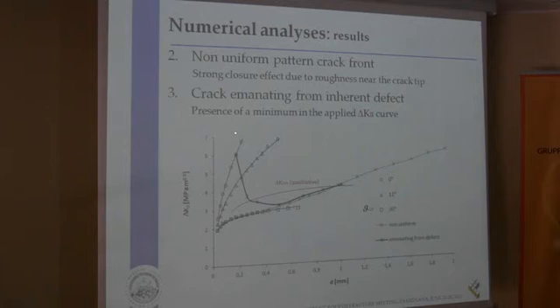And concerning the curve referring to the crack emanating from an inherent defect, we note that it starts from a higher value due to the presence of a flat crack, then it decreases rapidly, tending to the non-uniform pattern crack front. And so this curve presents a minimum, which means that if the applied stress intensity factor falls below the propagation threshold, a crack arrest is predicted by this law.